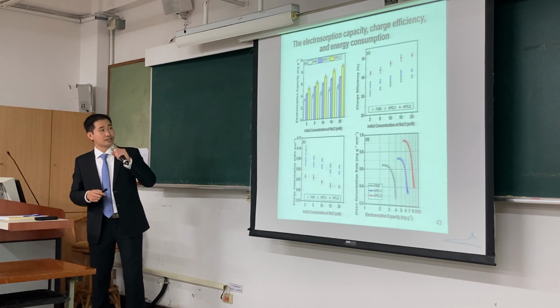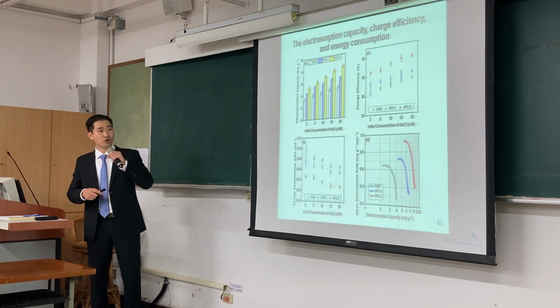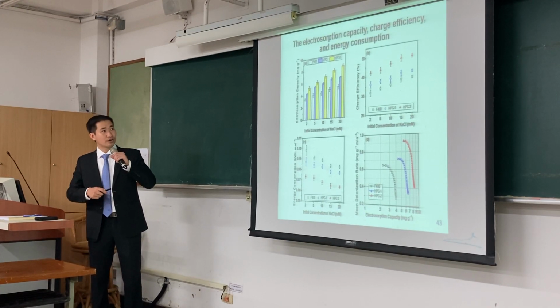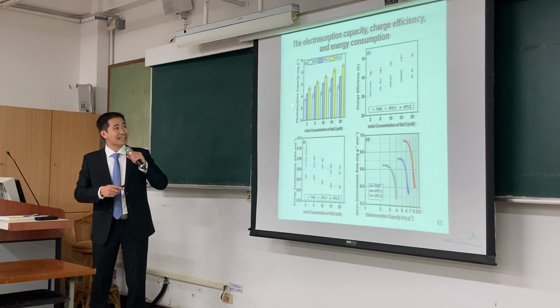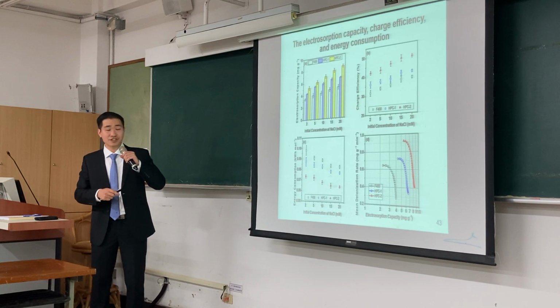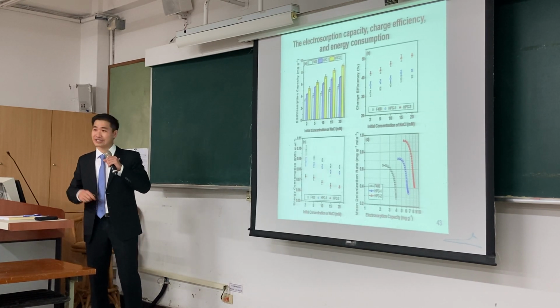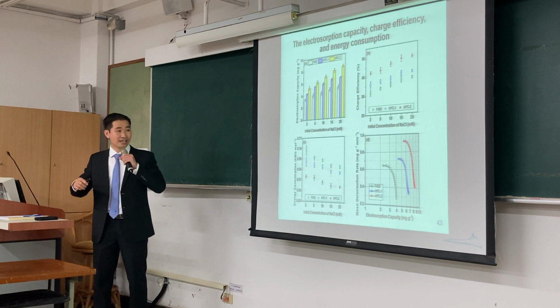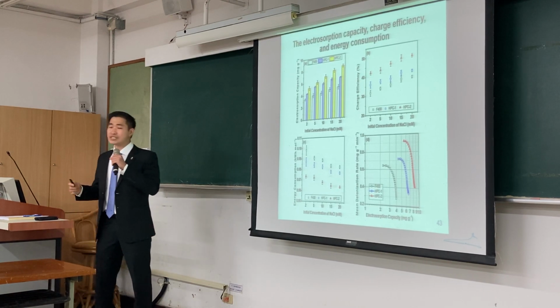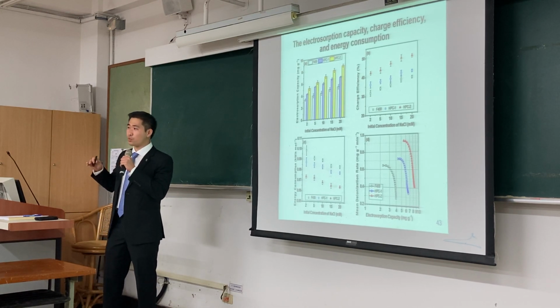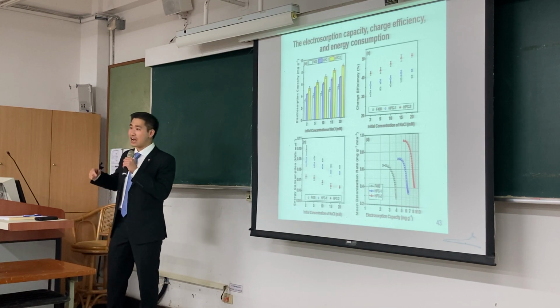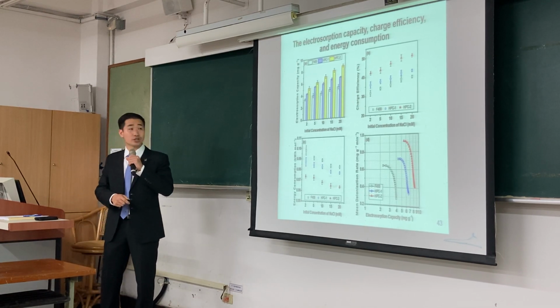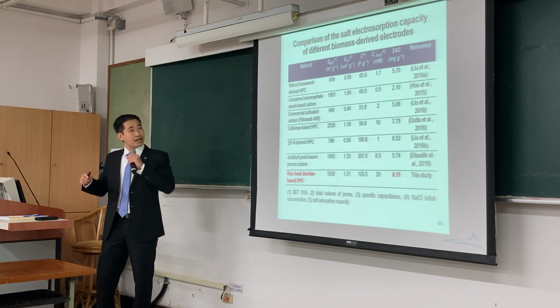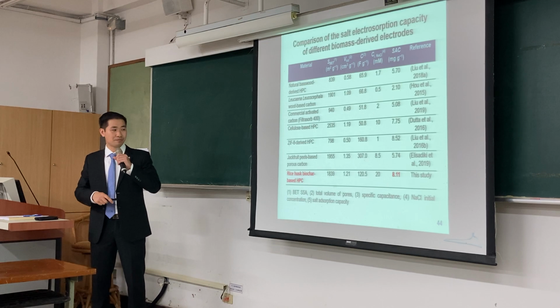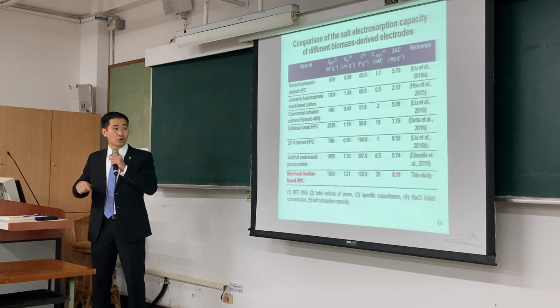Moreover, we conducted the effect of initial sodium chloride concentration. We can see that the electroadsorption capacity and the charge efficiency increase while the energy consumption decreases when the concentration of sodium chloride increases. As a result, the NBC material prepared from greenhouse biochar presents a higher electroadsorption performance compared to the commercial material. This table compares the salt electroadsorption capacity of NBC prepared in this study. It is higher than or comparable to previous studies.